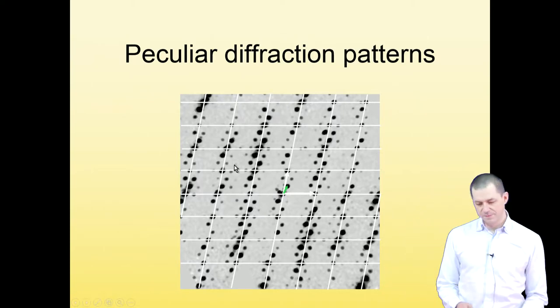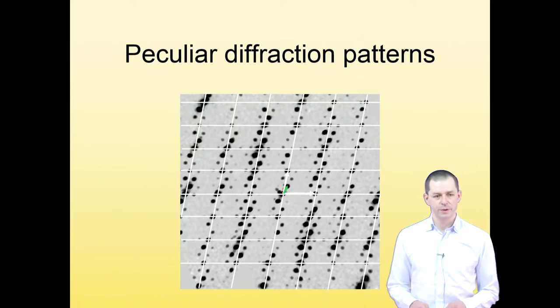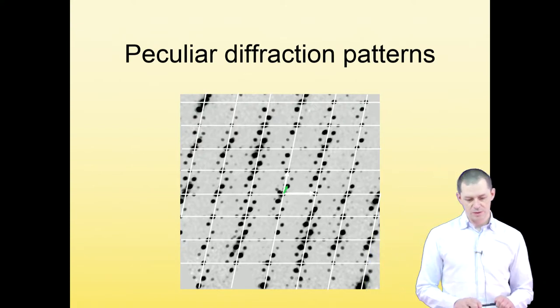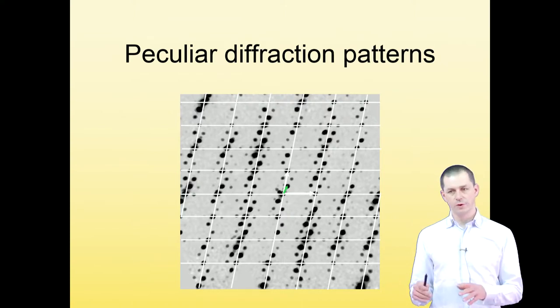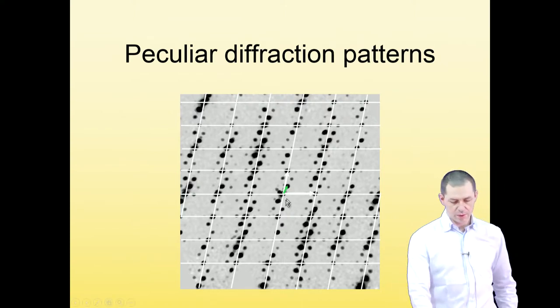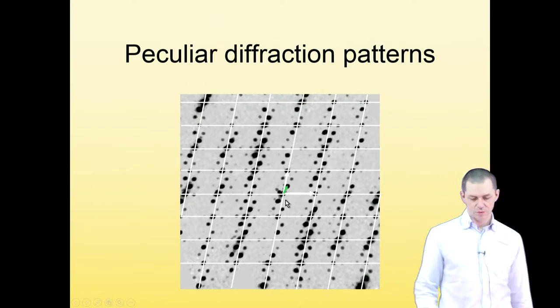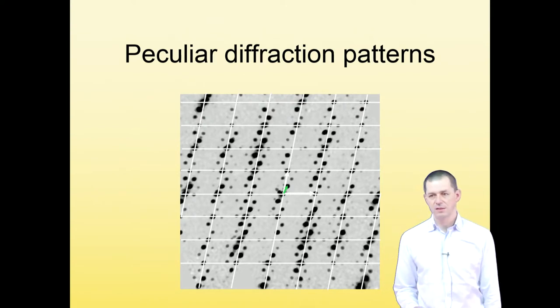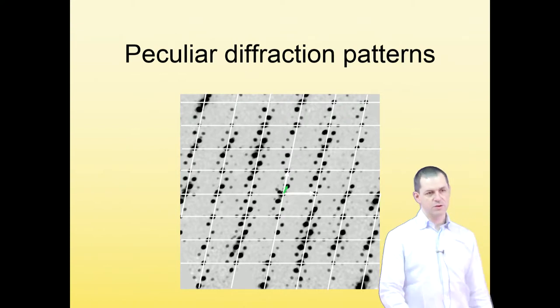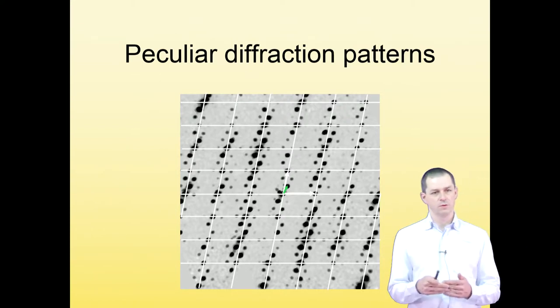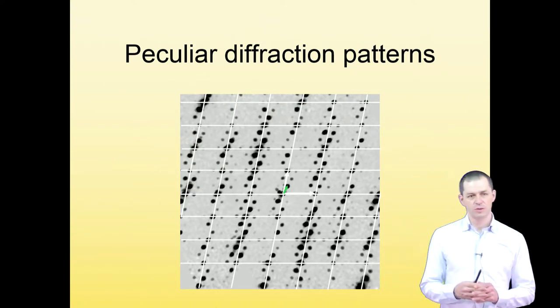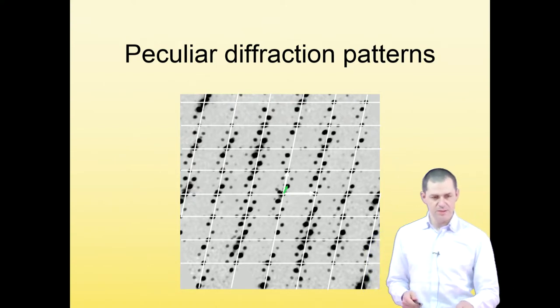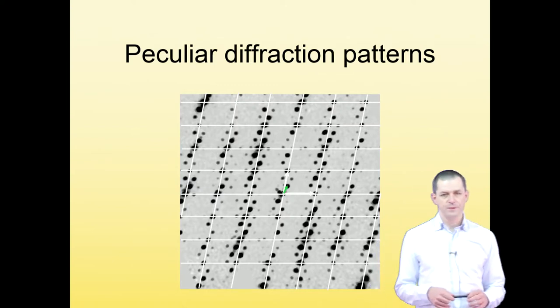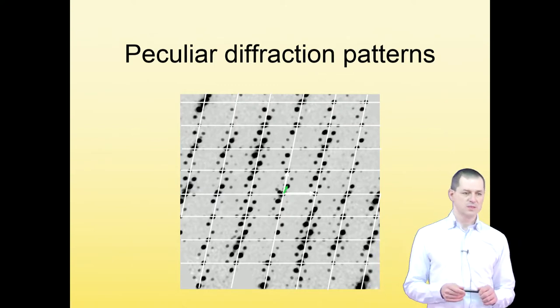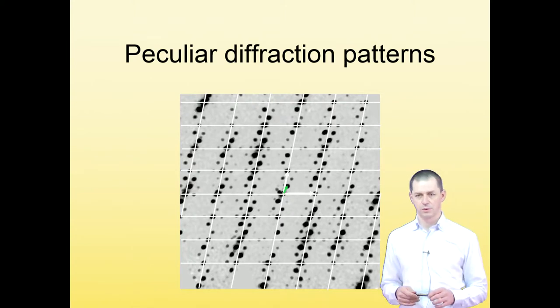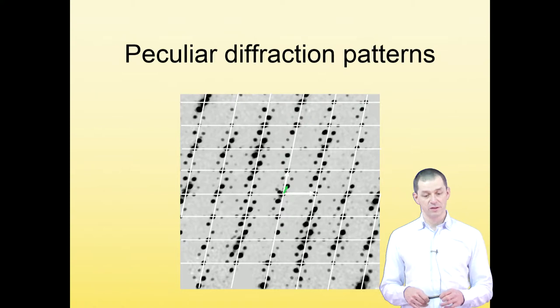So this is a particularly rich diffraction pattern. Quite often you find modulated structures where you find only one order of satellites. So these additional reflections which are away from the nodes of the average lattice, these are called satellites. And the number of modulation vectors you need to reach that satellite from the node of the reciprocal lattice is called the order of the satellite. So here we can see satellites up to fourth order. Quite often you can see satellites only up to first or second order. Third order is already relatively rare.